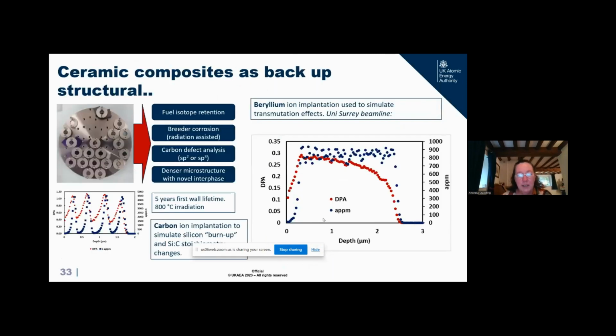And so I will end really with two quick last punchlines. The one is to say, you should always have plan B. If steel doesn't work, can we use ceramic composite? And in the same way that you've just seen me talk about artificially loading samples up with the effects of fusion, we're trying to do the same thing with silicon carbide ceramics, where we're loading them up, not just with damage in DPA, but we're loading them up with proxies for transmutation. We're actually putting other materials or other elements in and pretending that we have transmutation and generating the gases that we need to start to study the microstructural effects.